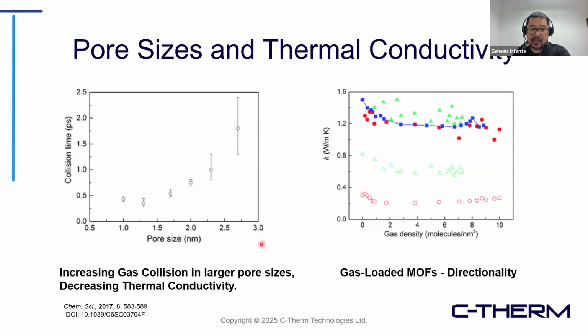Another correlation from the same paper is that a larger pore size typically means you'll have more gas contained within that volume, and having more volume means that there is a larger rate of collision between those gases within that pore, and that has a direct implication on the overall thermal conductivity. Meaning, you'll have a higher rate of collision, and that becomes essentially a source of heat loss within the system itself, which then lowers the thermal conductivity of the material altogether.